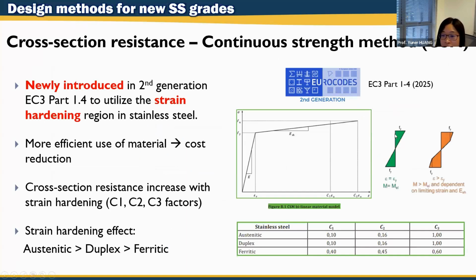And then in terms of the structural design, what is the difference between the different steel grades? In the second generation of Eurocode, they actually newly introduced a strain hardening region for the stainless steel. So in the past, the strain hardening behavior of stainless steel was not included in structural design, which is conservative for stainless steel. But in the second generation, they added the strain hardening using these strain hardening factors C1, C2, and C3. So in conclusion, if we include the strain hardening effect in the structural design, austenitic is the best, followed by duplex and ferritic.